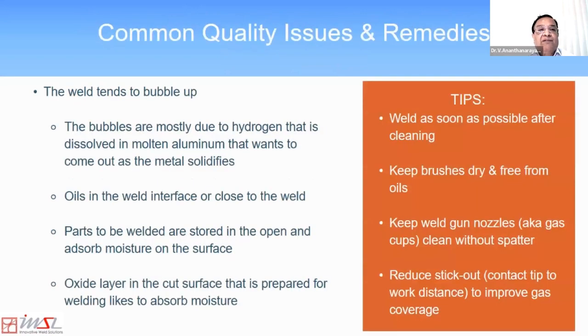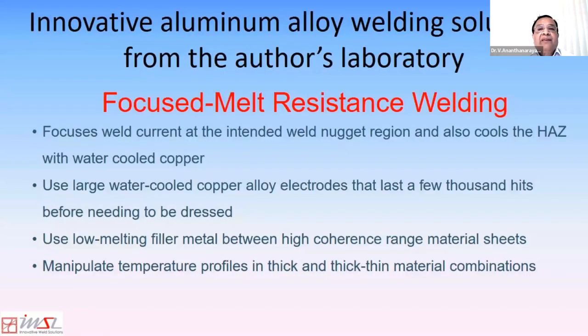And I've talked about the weld bubbling up already. I will talk about some solutions for some of these problems which were developed in my laboratory, which actually involved focusing weld current at the intended weld nugget region. And such focusing methods also permitted cooling of the heat affected zone with water-cooled copper. They use large water-cooled copper alloy electrodes that you would not find being commonly used in resistance welding.